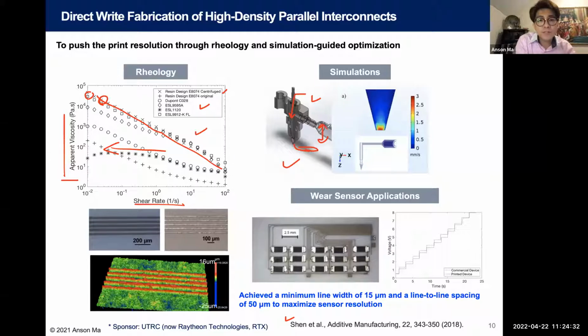If I'm in a very old building at a university that has very poor compressed gas supply, then you will have a lot of variation in pressure. As you perturb the shear rate, because the pressure also affects the flow rate, and the flow rate determines the shear rates, you will also have much bigger changes in the viscosity. So the only caveat I would say is that the higher the degree of shear thinning, the better, but it also puts more constraints on the pressure control, how well you can control the pressure. But if you're in a new building with a very nice compressor, that shouldn't be a big problem.